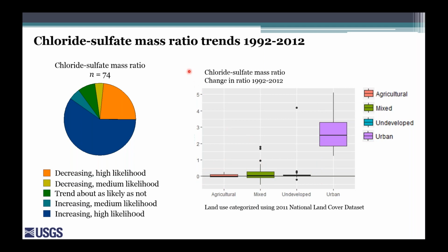Okay, and so this is very similar to the chloride concentration analysis where we're finding that urban areas are really changing most rapidly. And what we're seeing there are large increases in chloride as well as large increases in the chloride to sulfate mass ratio, which is known to cause the water to be potentially corrosive to water distribution systems.